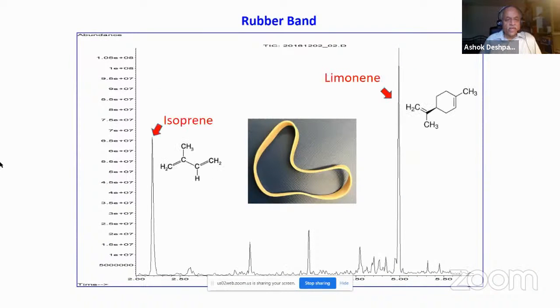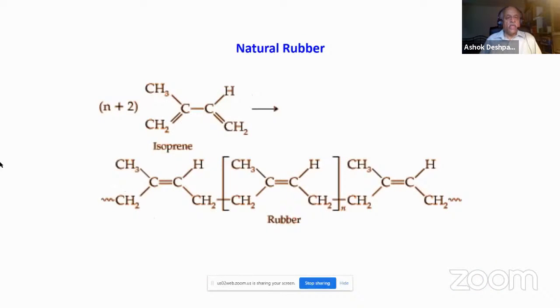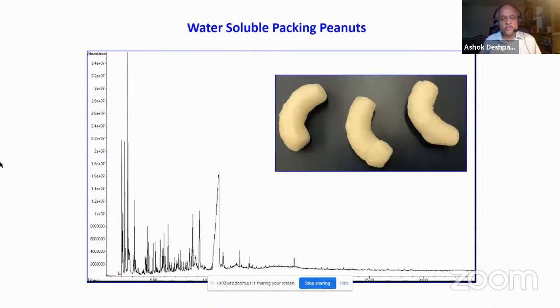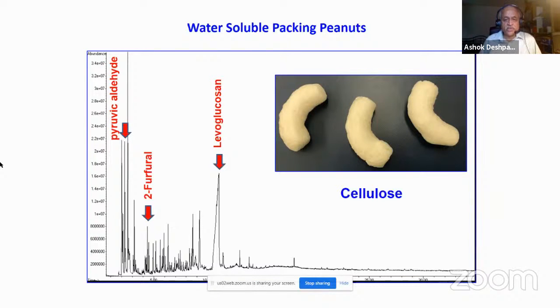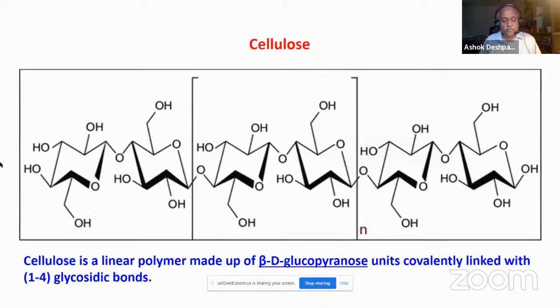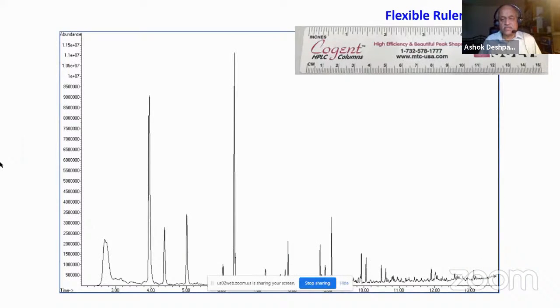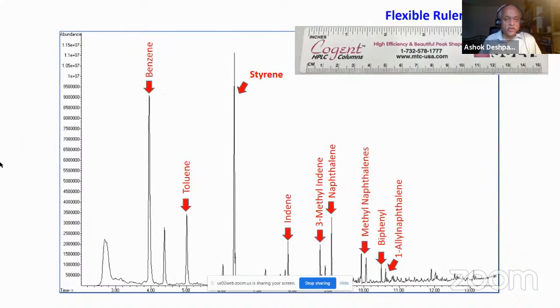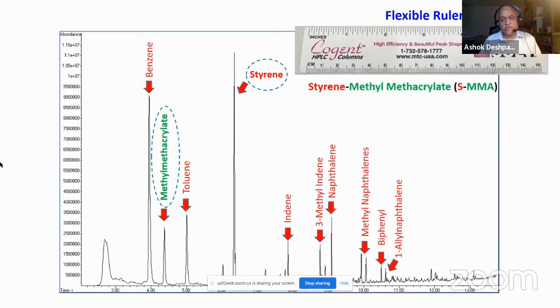The rubber band has limonene and isoprene as its marker compounds. So we call it natural rubber. The natural rubber is formed by the polymerization of isoprene. This water-soluble packing peanut has a signature of cellulose. Cellulose is formed by polymerization of beta-D glucopyranose. The last example has styrene and other aromatic compounds and also has methyl methacrylate. So we call it styrene methyl methacrylate.